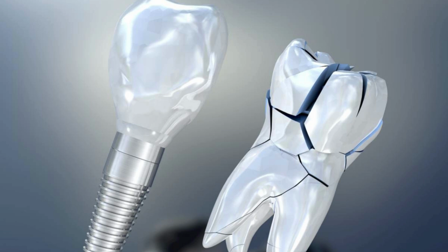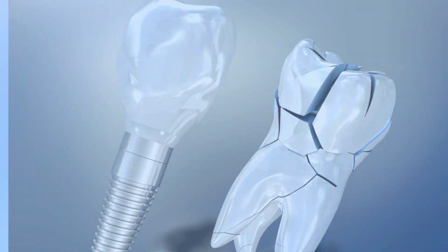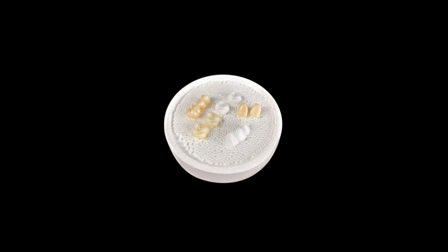6. Post-sintering adjustments. A major risk. Modifying zirconia after sintering, such as grinding or margin reduction, can easily introduce microcracks. Key insight: all adjustments must be made in the green stage, before sintering. In this pre-sintered state, zirconia is softer and safer to shape. After sintering, any mechanical adjustments should be minimal and carefully polished.